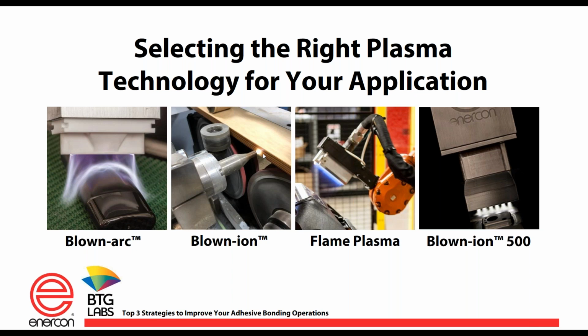It also is very ion dense, so the amount of ions coming out of that head is significantly higher than the blown arc, in a more concentrated area. And what that means is I can go a lot faster. I can treat up to maybe 100, 120 feet a minute, depending on the application. If I put 2 heads in parallel, I can treat much faster than that.